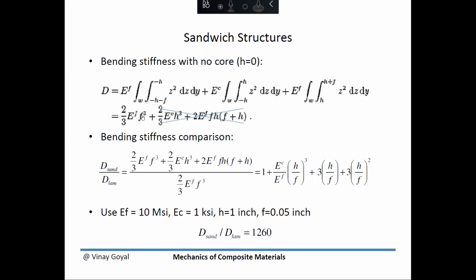The reason that's not showing up is because this bending stiffness is not the same bending stiffness as for a beam. In the beam, we have integrated through the thickness, but also through the width. While for plate theory, we have only integrated through the thickness, and that's why the width is not showing up here. But this is very similar to EI that you have gotten for a beam, except without the b for the width. So with no core, you get this expression.